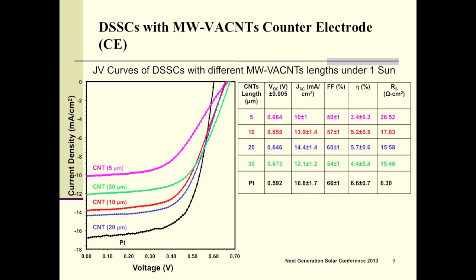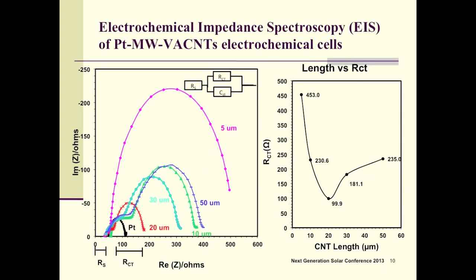So what is actually happening for the longer carbon nanotubes after 20 micrometer? In order to understand that, we used many characterization techniques. One of the techniques we use is electrochemical impedance spectroscopy, in order to understand the charge transfer resistance at the carbon nanotubes and electrolyte interface.